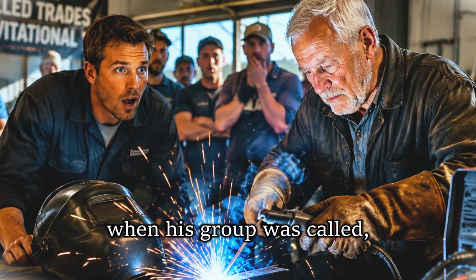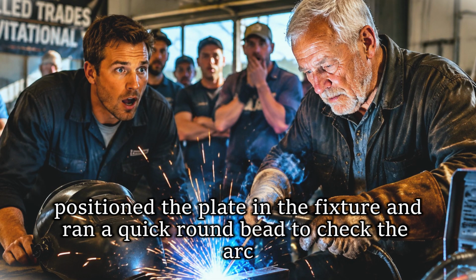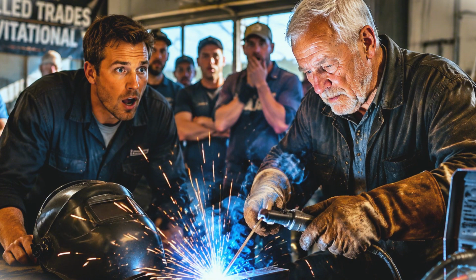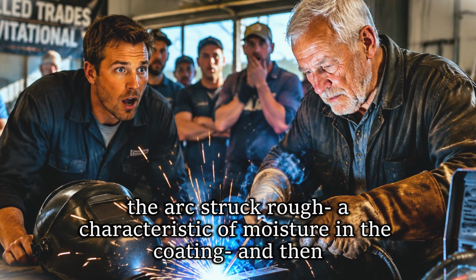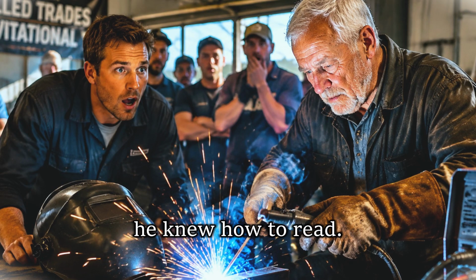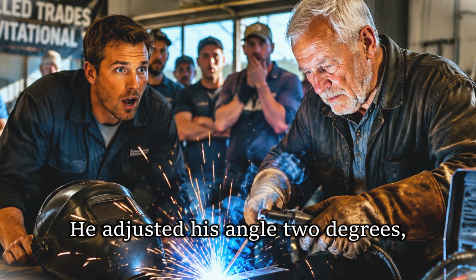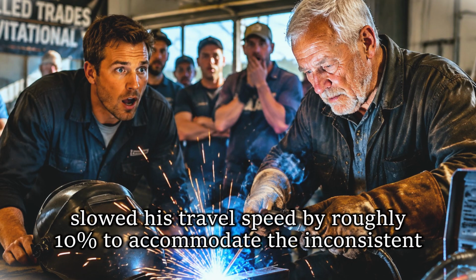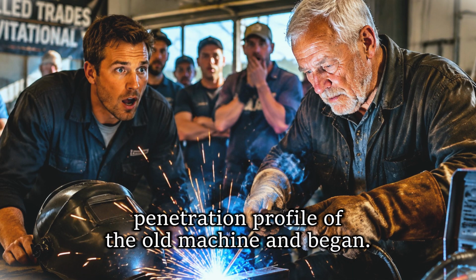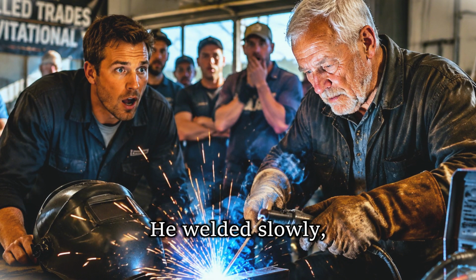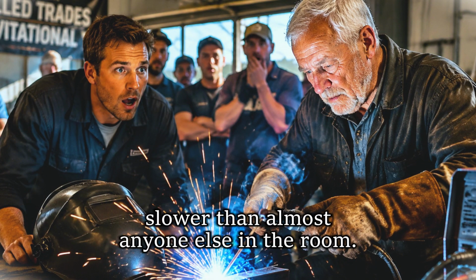When his group was called, he walked to the station, positioned the plate in the fixture, and ran a quick ground bead to check the arc quality before the clock started. The arc struck rough, a characteristic of moisture in the coating, and then settled into a rhythm he knew how to read. He adjusted his angle 2 degrees, slowed his travel speed by roughly 10% to accommodate the inconsistent penetration profile of the old machine, and began. He welded slowly, slower than almost anyone else in the room.